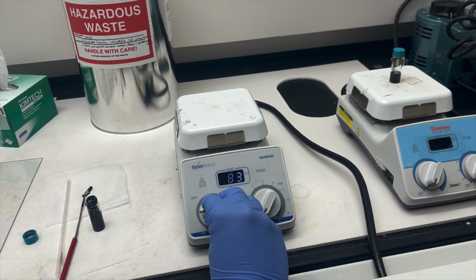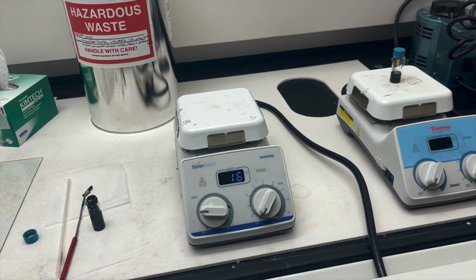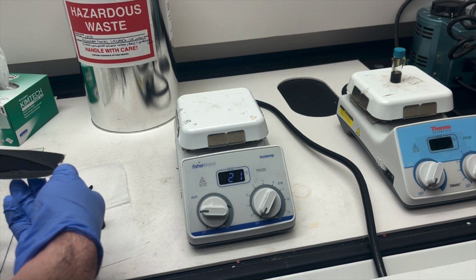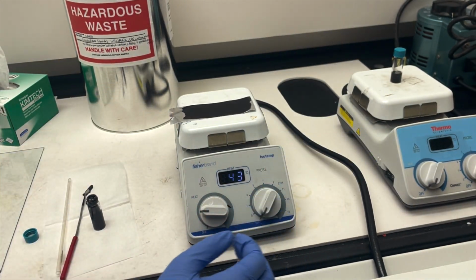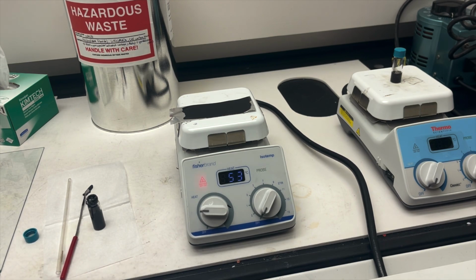Here, I am turning on the hot plate to 80 degrees Celsius and then transferring the foil, taking care to keep it as flat as possible. It would be better to place the foil on the hot plate before turning the knob to the desired temperature. If we shock the slurry with heat right away, the evaporation of the NMP solvent will occur too quickly and leave the material cracked and uneven.